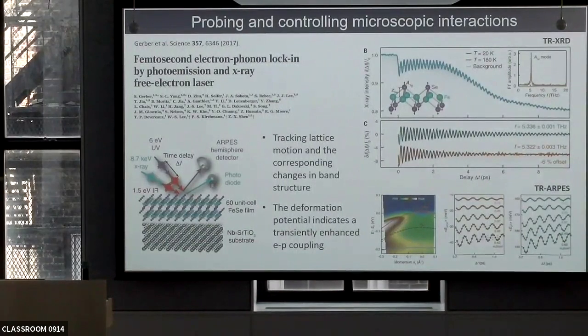So in other words, you're looking at some bands below the chemical potential, you're modulating the particular mode, and as that mode is modulated, also the bands will of course change. And the conclusion of this was a transient enhancement of electron-phonon coupling. Now, one limitation of this experiment I'd like to highlight, because it's important, is that all of the photoemission data is taken close to the gamma point, again because of the limit in photon energy of this photon, 6 to 7 eV usually.